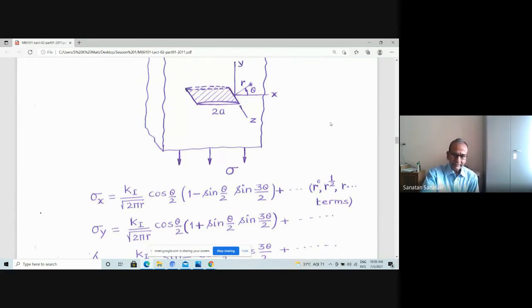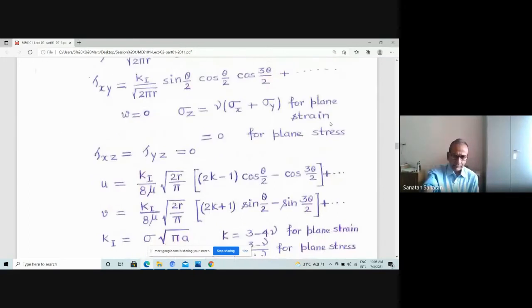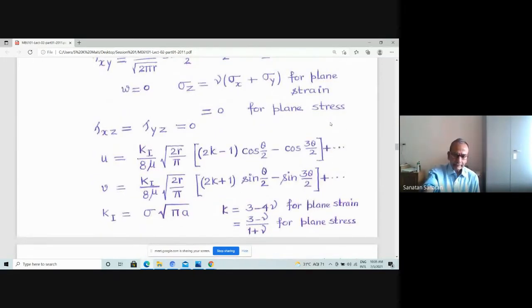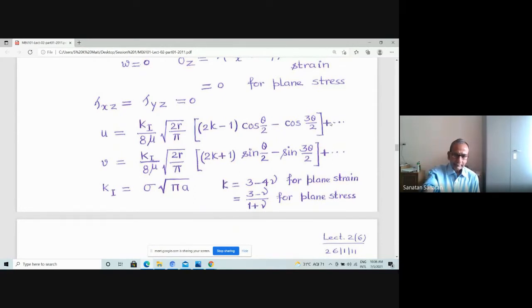So that stress field around the crack was obtained by him, and this is the form of it. So sigma x is the stress which is acting parallel to the x direction, the crack plane direction. It has a form of that. It has one parameter which is K subscript 1, mode 1, and then that theta function. It is a function of r and theta, the distance from the crack tip, and theta the angular disposition. And then these displacements around the crack tip, and this parameter K1 is given by the load that is applied remotely and the crack size.